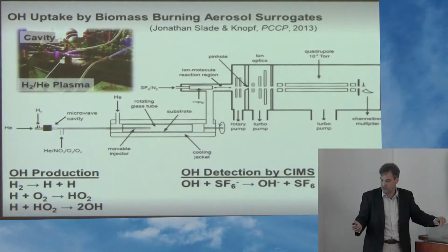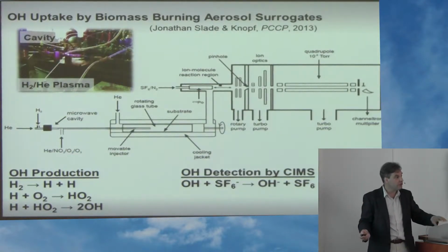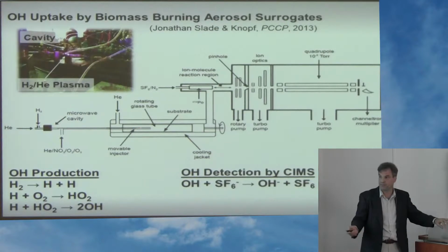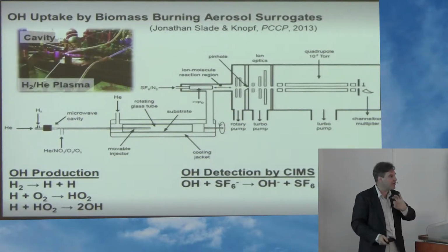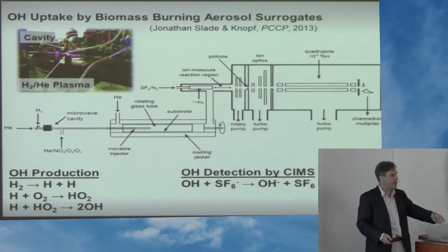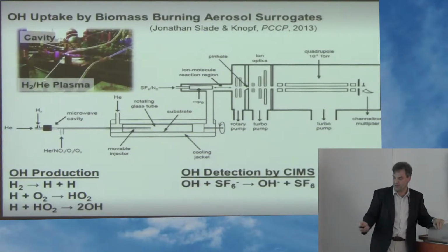They're tubes, and we operate at low pressure to avoid any diffusion effects. We make OH by using a hydrogen plasma with a microwave cavity — really old school atmospheric chemistry, done by Ferguson, Molina, Sherwood in the 70s. The H reacts to completion to form 2OH. It's a very clean source; no other chemicals are involved.